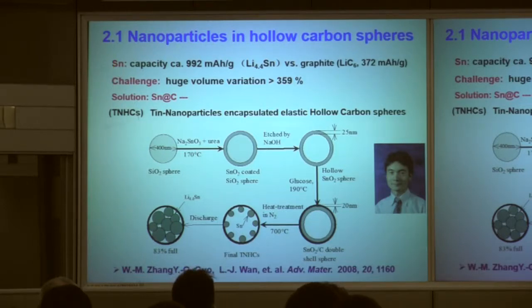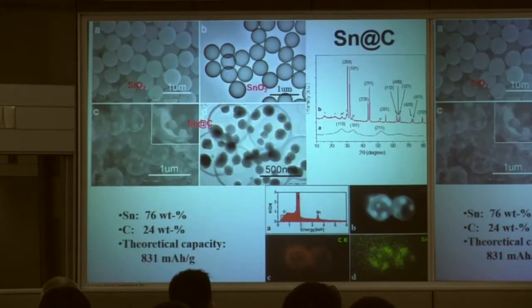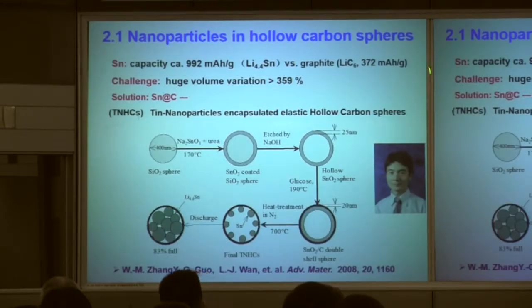Tin is also a very good electrode material for lithium-ion battery. The theoretical capacity, almost 1,000, is very high compared to other materials. But the weakness is volume change during charge and discharge. So that means the small tin nanoparticle is not stable during the charge and discharge process. So we think if we can make a small nanoparticle and then put all of the nanoparticles together in a carbon sphere, in this case, all of the tin nanoparticles are covered by a confined space. So this small nanoparticle should be stable, and the structure will be stable.